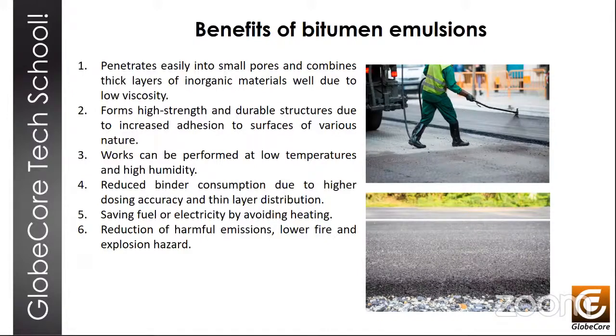The third advantage is the ability to operate in low temperatures and in high humidity by improving the adhesion forces of the binder to the surface of the stone. In this case, the moisture content of the inorganic material, the minerals, actually plays a positive role when combined with a bitumen emulsion.